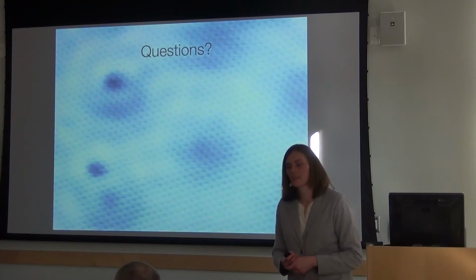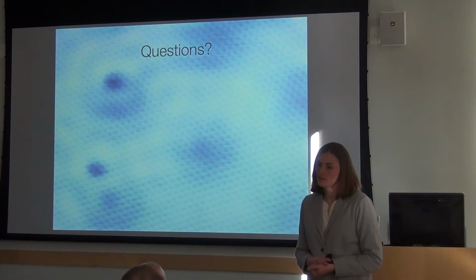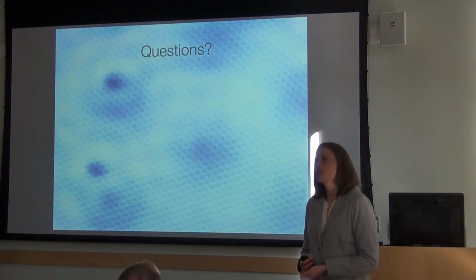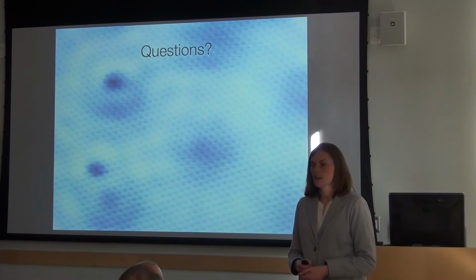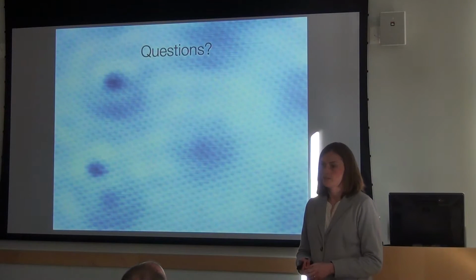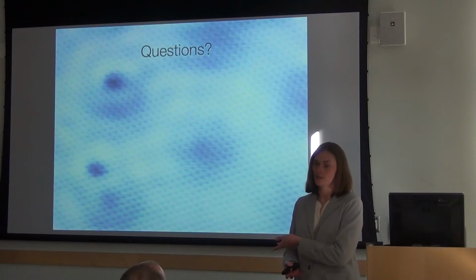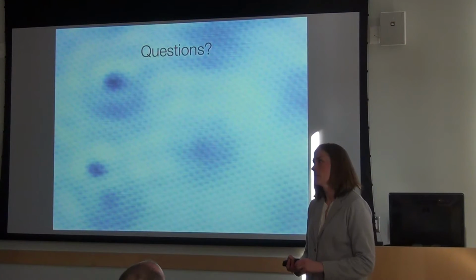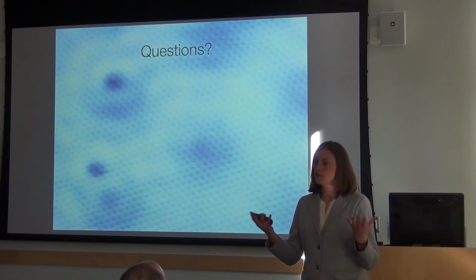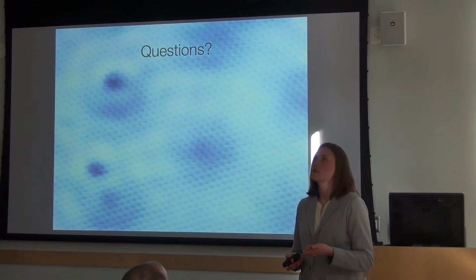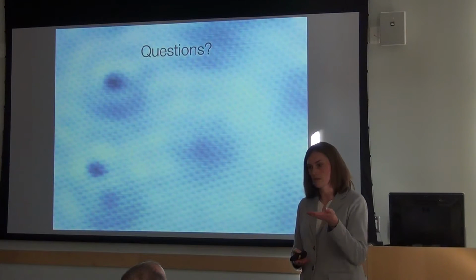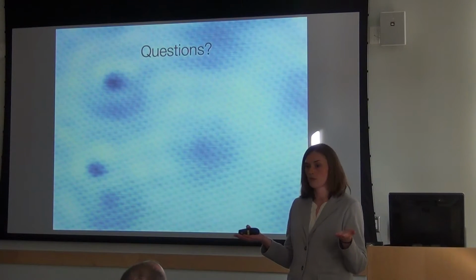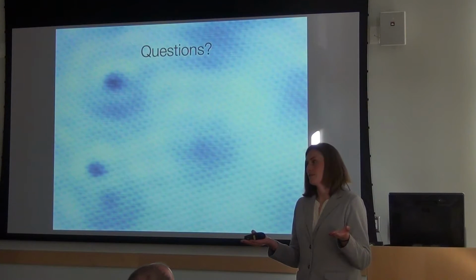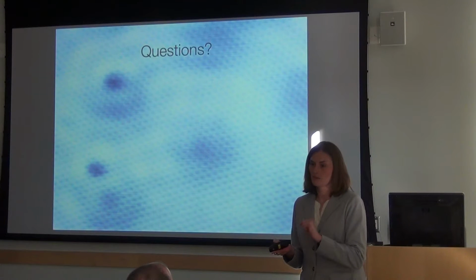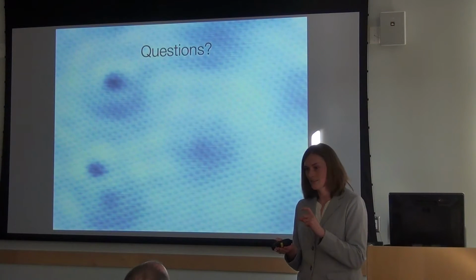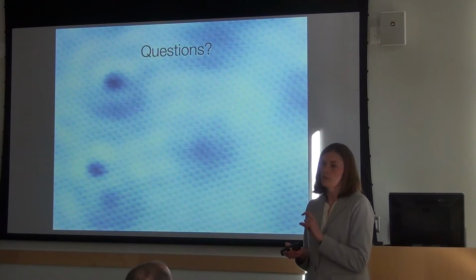In forming the graphene, do you think there's any problem with hydrogenating both sides of the graphene sheet, or are you getting just the top surface? It's very unlikely that we're affecting only the top surface. People have shown very good intercalation of big things like lithium underneath graphene, between graphene and copper. It could be a little bit different in our case since we grow in UHV and those are grown at atmospheric pressure. So there are some variations in STM results of UHV grown and atmospheric pressure grown CVD graphene because of the interface between graphene and copper in the CVD case. So there may be differences because that interface is probably really important.